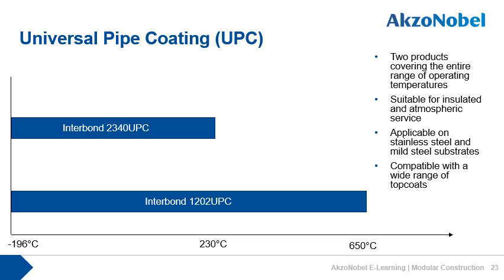Next, we come to the concept of universal pipe coatings. The name really says it all, and this is where we just have one or possibly two products which are specified on all pipes and vessels, covering the entire range of operating temperatures, insulated or atmospheric service, and covering different substrate materials. In our case, we have Interbond 2340, which can handle temperatures from cryogenic up to 230 degrees C or 446 Fahrenheit. Importantly here, it also shows excellent performance at ambient temperatures in atmospheric exposure. And this is something that phenolic epoxies fall short of.